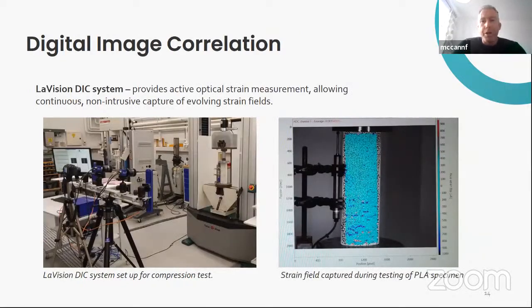And another one of the new toys, I suppose, that we've gotten over the past few years is a digital image correlation system from LaVision. Recently, so this is the polylactic acid tubes, the 3D printed tubes. And you can see here that we're able to extract an evolving strain field during the tests. And as we move into more specific material processes and more bespoke geometries and so on, we're going to need to be able to locate where stress concentrations are happening. So stress via strain concentrations. And the DIC system is exactly what we need for this.